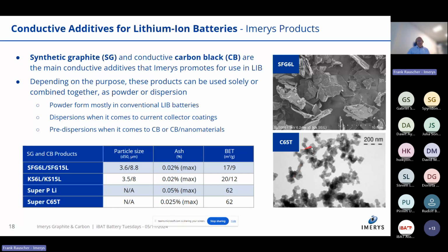Basically, those pathways that you see here for carbon black, those are the pathways for lithium ions or electrons to travel in the anode and cathode. The higher the structure, the smaller the primary particles, the better the conductivity of this material, and the less you need to use in a cathode or anode formulation.